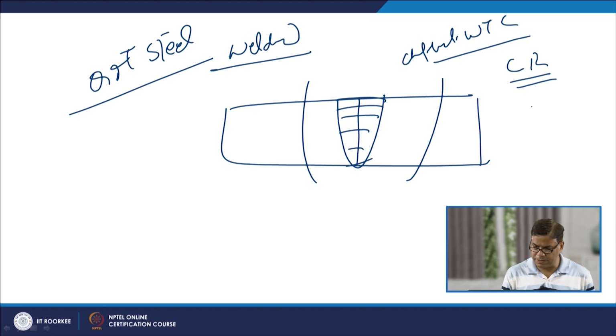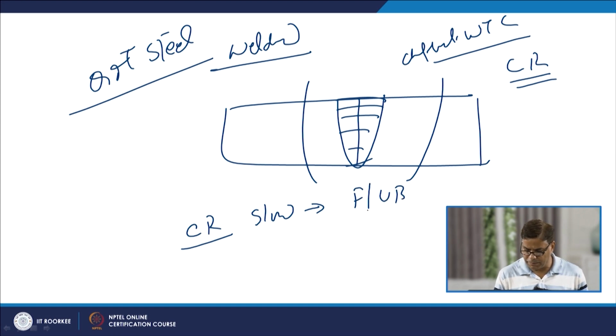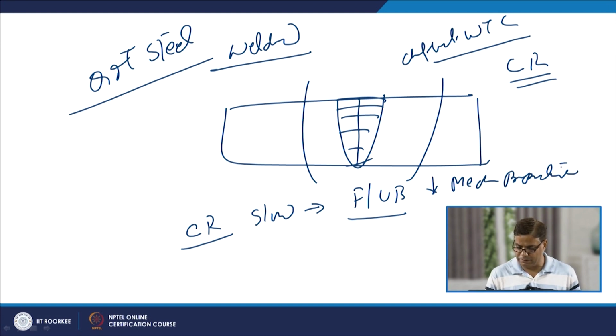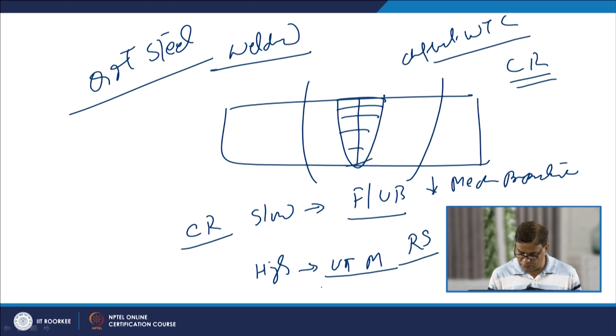But if the cooling rate is unfavorable, very slow, then it will lead to the formation of ferrite and upper bainite only, which lowers the mechanical properties significantly. So, there is a deterioration in mechanical properties in terms of notch toughness and yield strength. When the cooling rate is extremely high, it will lead to the formation of untempered martensite. The development of residual stresses in combination with untempered martensite will increase the cracking tendency, defeating the purpose, as the weld joint is being made with a defect.